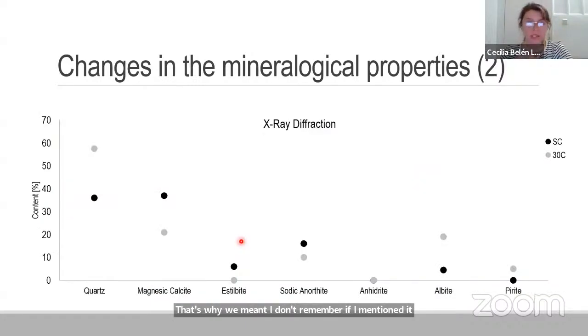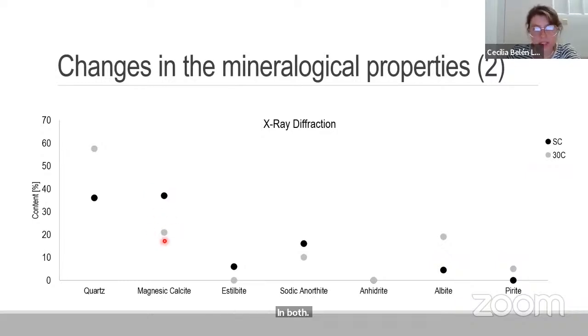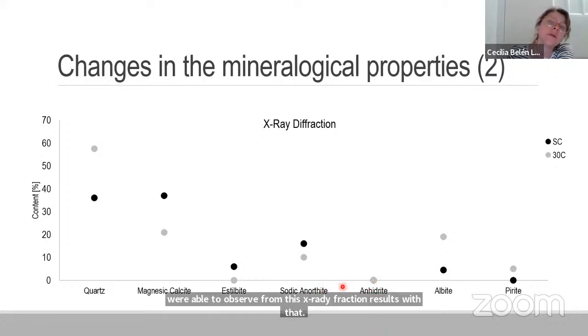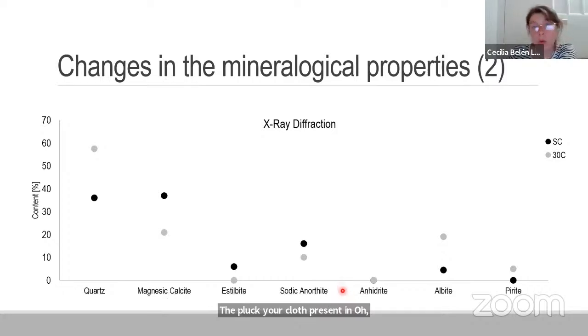We also performed a series of X-ray diffraction tests in both pristine and carbonated sandstone. What we were able to observe from these X-ray diffraction results was that the plagioclase present in our sandstone was mainly anorthitic and, in less amount, albitic.